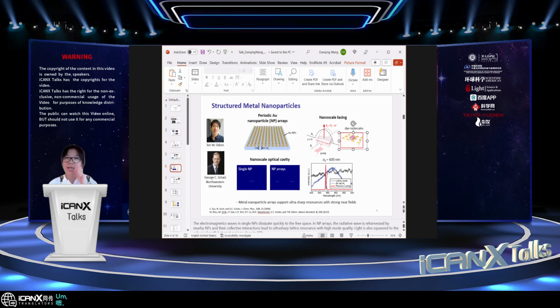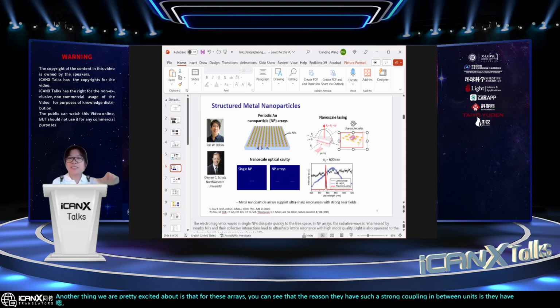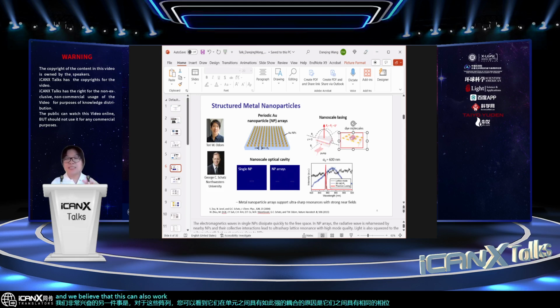Another thing we are pretty excited about is that for these arrays, the reason they have such a strong coupling between units is they have identical phases between each nanoparticle. And we believe that this can also work as a framework where we can put emitters at different sites of these nanoparticles and look at these long-range couplings in between, where the underlying cavity serves as the channel or the framework.